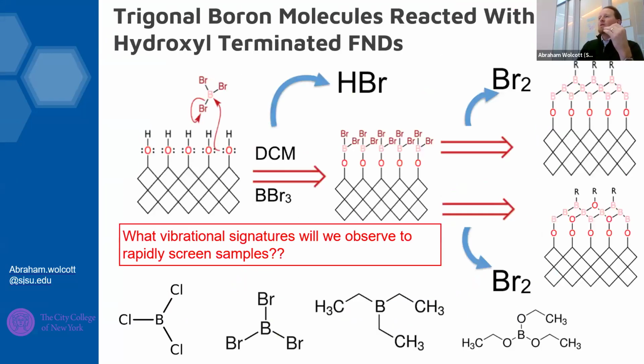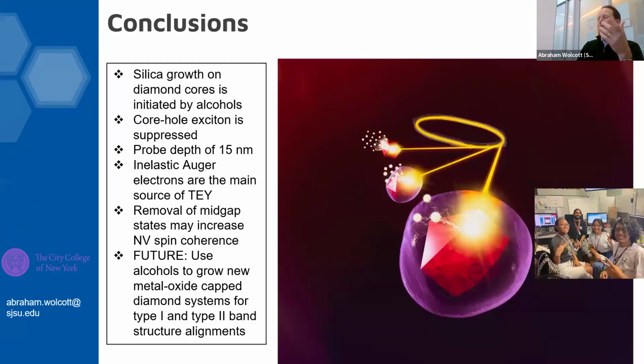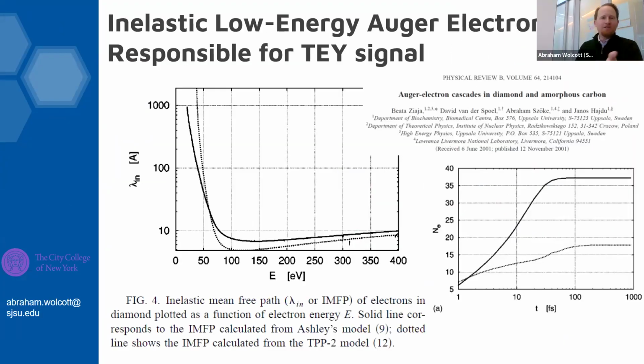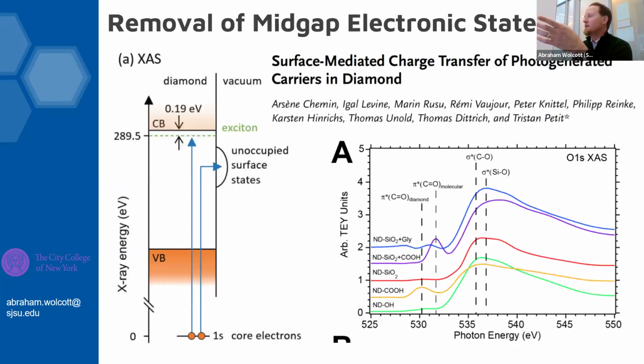Yeah, so the overall hosting of electronic noise on the surface of the diamond, to your point, maybe it's getting screened by the silica, but the silica is ultra thin. So I guess we'd have to model it. And I think Peter Maurer did a wonderful job summarizing some of that band bending and the removal of some of these occupied states. And I think what we can see using our spectroscopy is that if in fact it's a combination of both, a band bending mechanism to remove electronic density, and you're also shielding some sort of transient, static charge in conjunction with these mid-gap states, I think we're much better placed to understand the real decoherence mechanism.